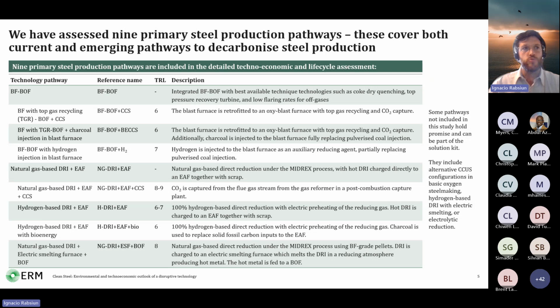And the final pathway is one where after the natural gas-based direct reduced iron, there is an intermediary step where there is an electric smelting furnace. This is a pathway that is being considered by some steel makers because it allows for the continued use of lower grade pellets. Direct reduction pathways typically require a DR grade pellet that is higher quality and represents a very small share of total merchant iron. So to address that limitation, we included this pathway here.